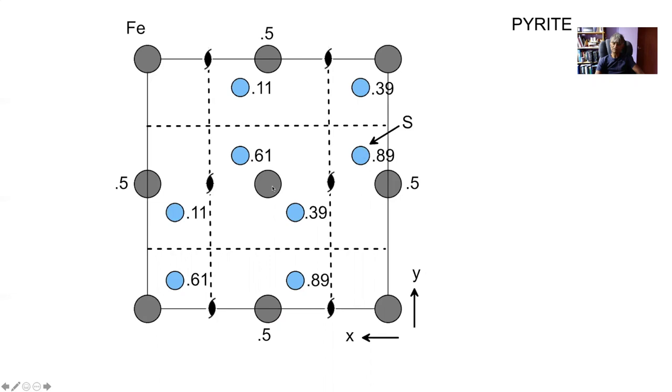So this is an iron atom at 0, 0, 0, rotate by 180 degrees and translate by half of the repeat distance normal to the diagram. So these are screw axes, which when looking at the macroscopic symmetry, would appear like a dyad because you do not pick up these very small translations on a macroscopic scale.